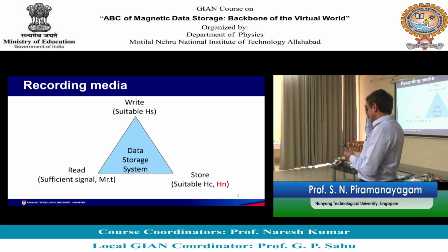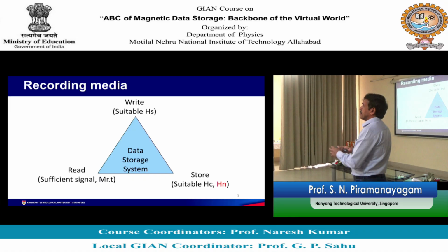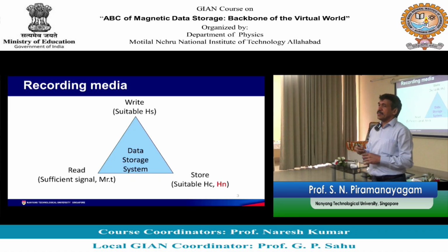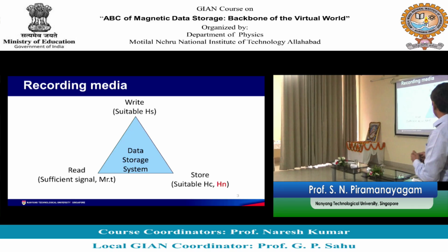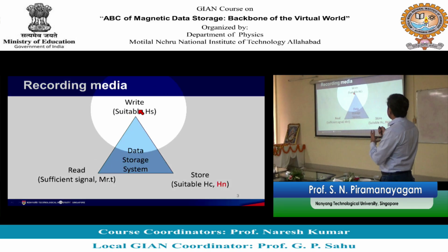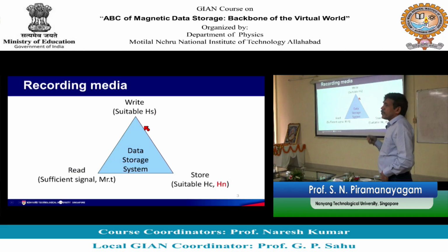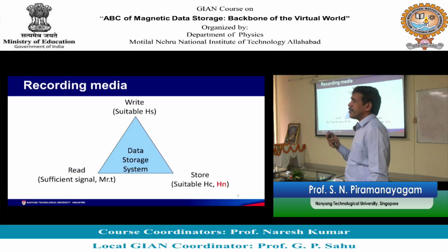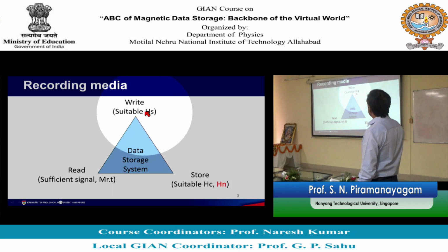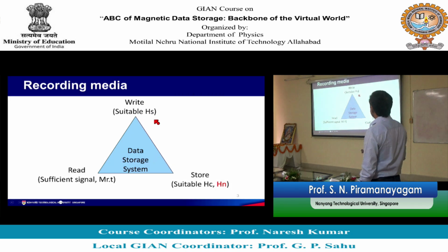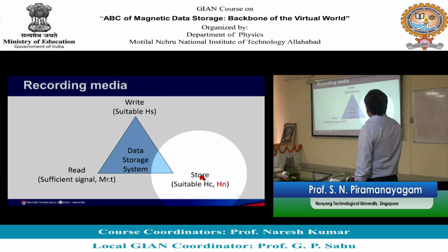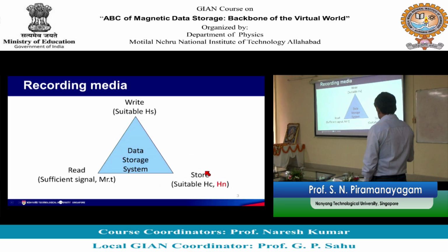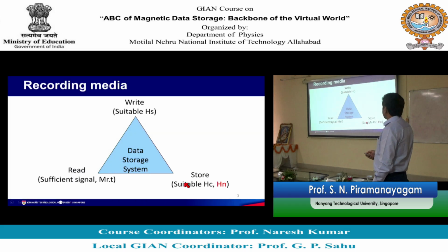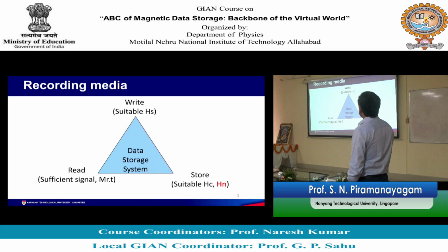And when you create recording heads, because of the spacing and all those things, you will be able to achieve 1.5 Tesla or so. So you have a write field of 1.5 Tesla, and if your saturation field is more than 1.5 Tesla, you cannot write information. So we need to have suitable saturation field, and for storing information, we need suitable coercivity, nucleation field, and so on. And when we talk about reading information, we should have sufficient signal, low noise, and optimized MRT.